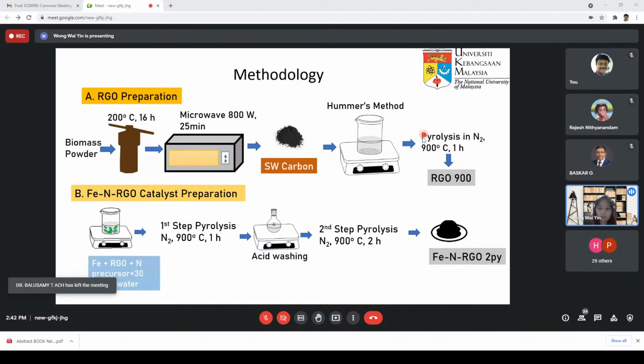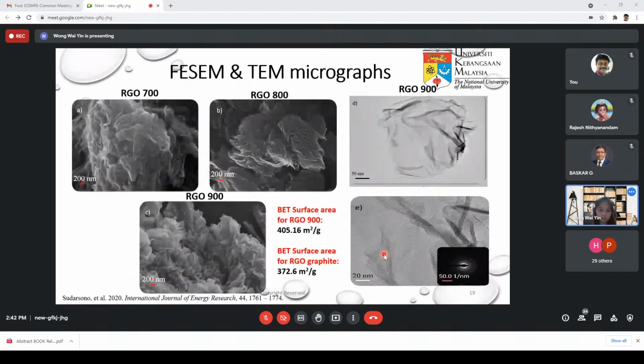Since the pyrolysis process is the same, the product from here will directly mix with the iron salt and also the nitrogen precursors and be subjected to pyrolysis. So we attempted a two-step pyrolysis in order to examine the difference between the first step pyrolysis and the second step pyrolysis in terms of the ORR activity and also the morphology.